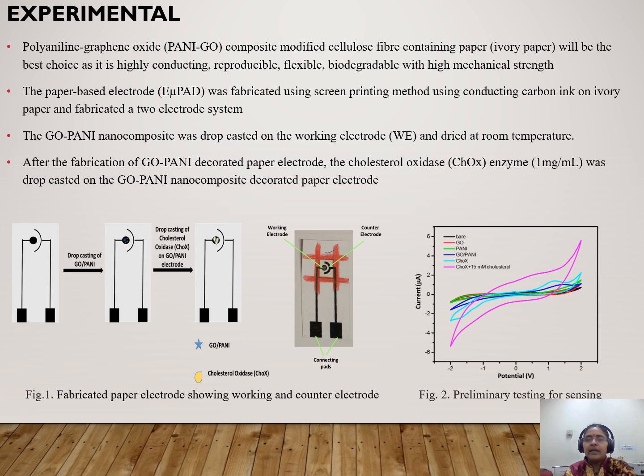After that we put polyaniline itself, and it did not give very good current. Therefore the GO-Pani composite was put, and this blue curve shows the GO-Pani composite. We can see the cyclic voltammetric curve here, and then after immobilizing the cholesterol oxidase, the current is further increased, and this light blue curve shows the cyclic voltammetry of the GO-Pani ChOx electrode. Upon that, 15 millimole cholesterol was added and the current increased drastically. That means this electrode is good for sensing cholesterol.